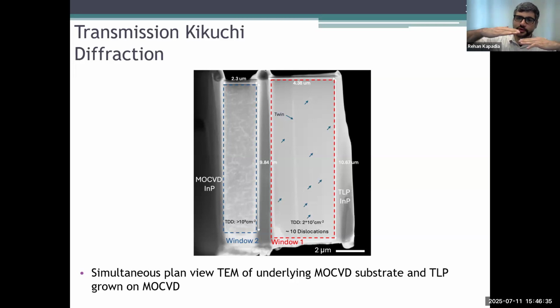And let's actually go through and do plan view TEM. So we take the sample and basically shave it off so that we can see a slice of the underlying substrate, and a slice of the TLP grown material. And so what you see here, when you actually take those slices, is that there is just extraordinarily high defect density in this underlying layer.